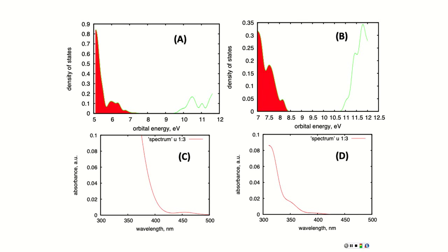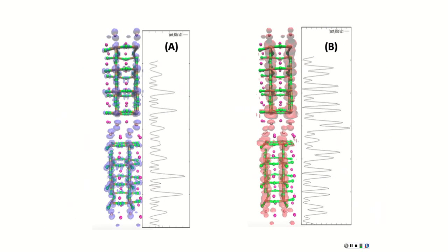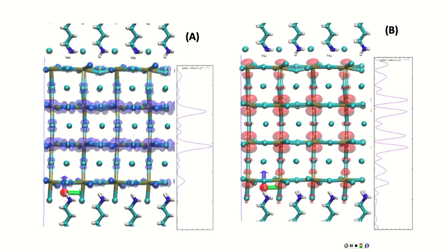So the larger band gap having HOMO-LUMO orbitals, and again show everyone where the orbitals are located. Okay, so they are on this intermediate, connecting inorganic atoms between the unit cells, the iodine and cesium layer. Now go to the case A for the DOS. Okay, and here's your HOMO-LUMO, and they do not really sit on this. No, they're only in the perovskite here. So probably this is the reason, right? That you have this contribution of organic molecules, right?